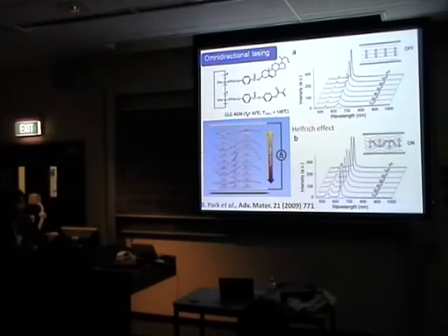Sometimes people misunderstand because, by applying the field, the cholesteric reflection color changes from the normal direction, so they think that they can tune the pitch. However, it's not true. The main reason could be this kind of Helfrich effect.